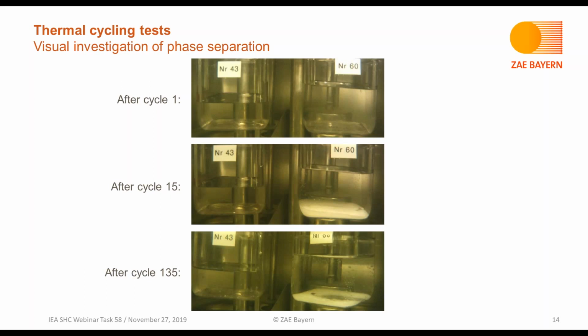At the top, you see the situation after the first cycle. So both samples shown here are completely in the liquid state as they should be. So this is the situation after cycle 1 at the high temperature. However, after cycle 15, you can see for sample number 60, there's some kind of solid material at the bottom, which indicates phase separation. And then continuing the cycling after cycle 135, there's still some solid material on the right sample at the bottom, but what is also visible is that the amount has slightly decreased.